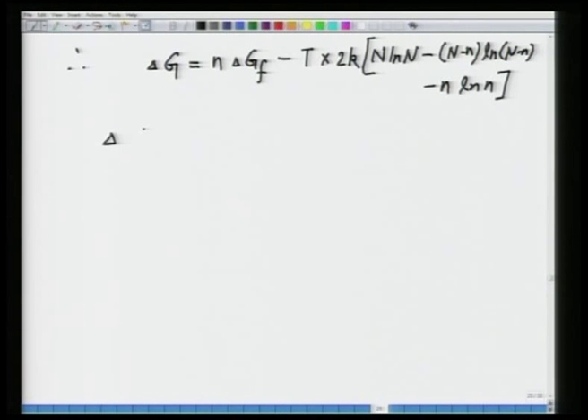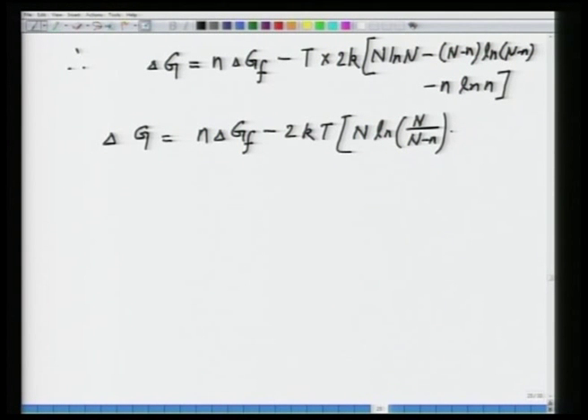So, this delta G, now you can write it as n delta G_F minus 2kT into, if you rearrange these, what you will get is N ln of N divided by (N minus n) plus n ln of (N minus n) divided by n. This is what you are going to get if you rearrange these. Okay, that's very simple. You just need to open this up. So that will give you the form.